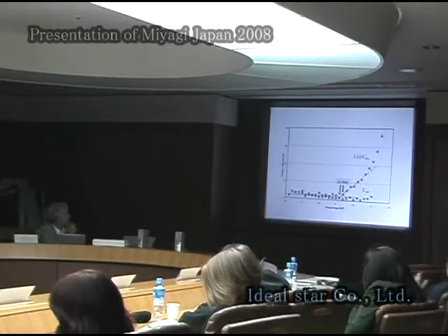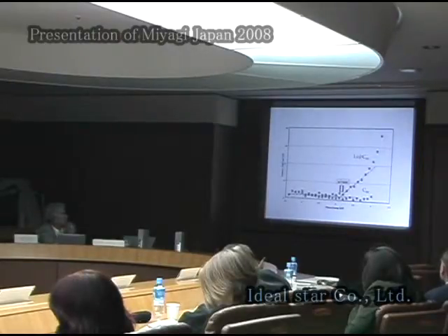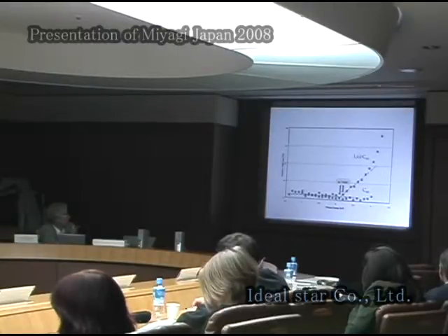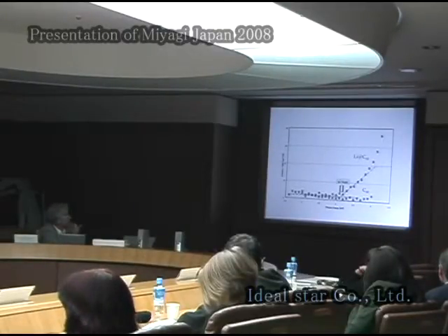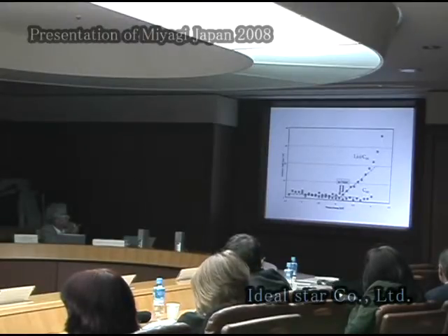For example, this is a photoemission spectrum. You can see the left side shows the emission spectrum of endohedral lithium fullerene, and blue is empty carbon 60. You can see 1 electron volt of energy is lower compared with the energy of carbon 60. These characteristics are very, very important for